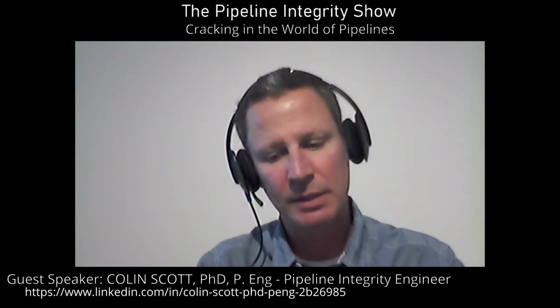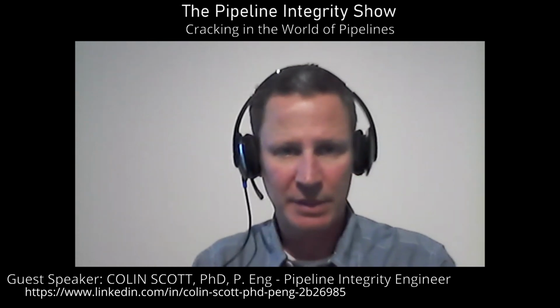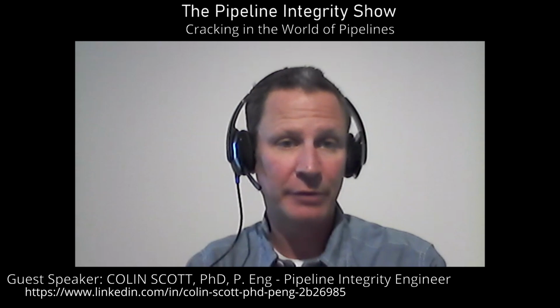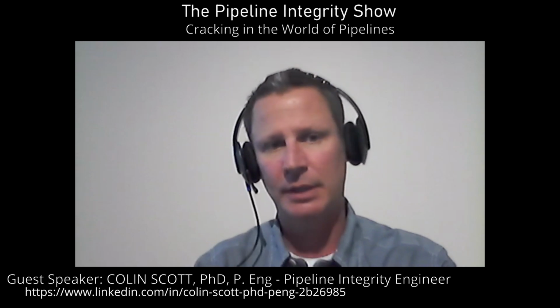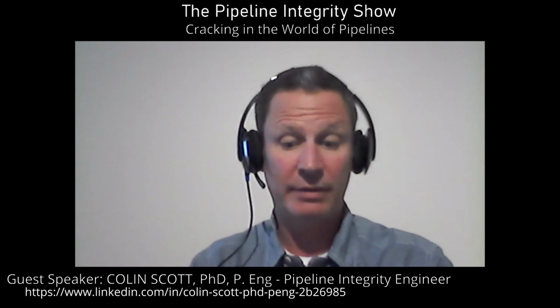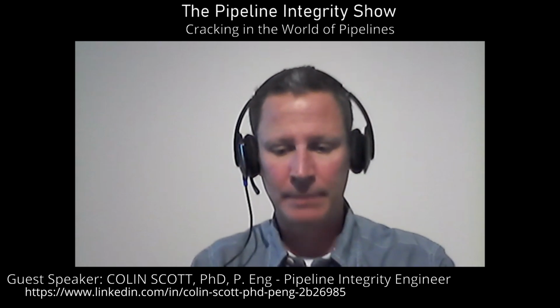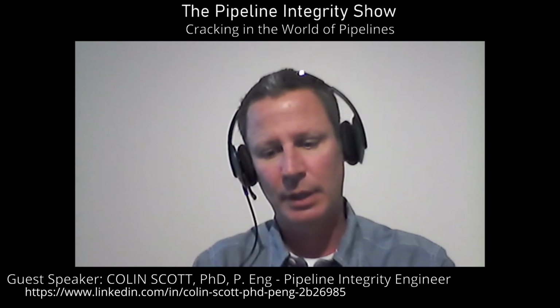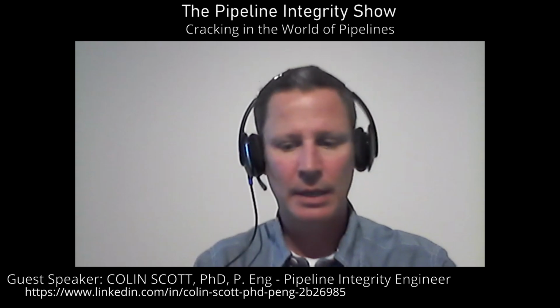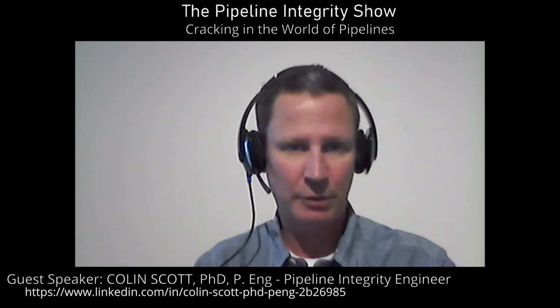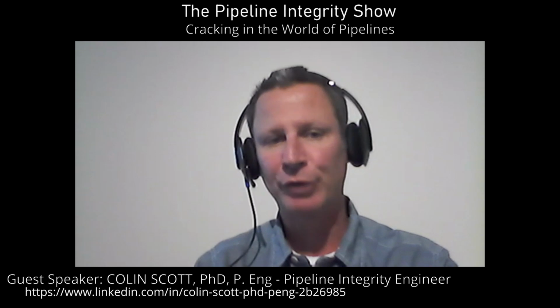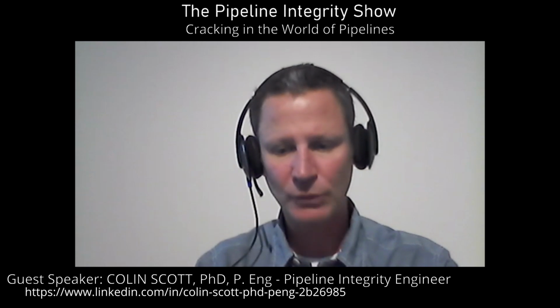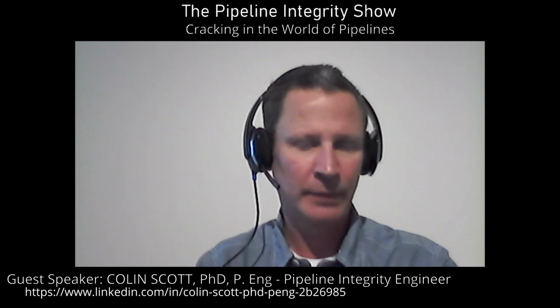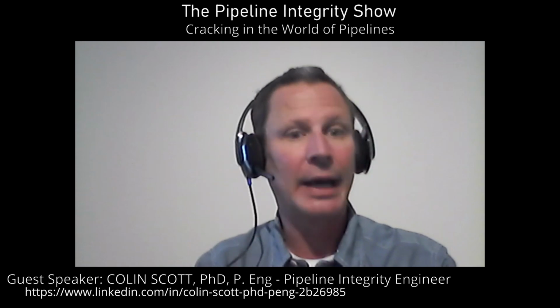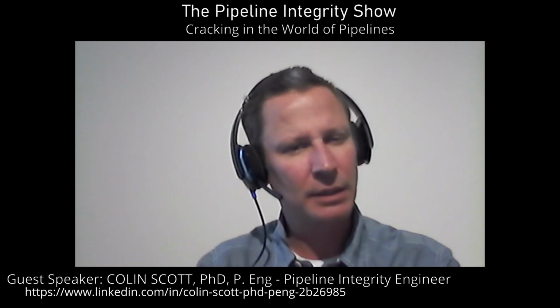So that's one mechanism. The other mechanism that sometimes comes into the conversation is hydrogen generation and hydrogen getting pulled into the crack tip. The problem with that is that if you have hydrogen up in your crack tip, the hydrogen can get into your atomic lattice, and it can disrupt the movements of dislocations. And so you're really embrittling the material right at the crack tip. You're not allowing it to yield and absorb energy. So sometimes you'll hear about a hydrogen-based mechanism. So it's a little bit different from what we have with fatigue.